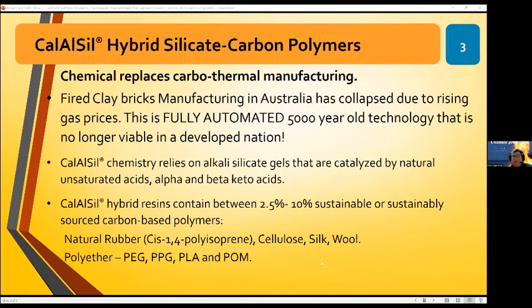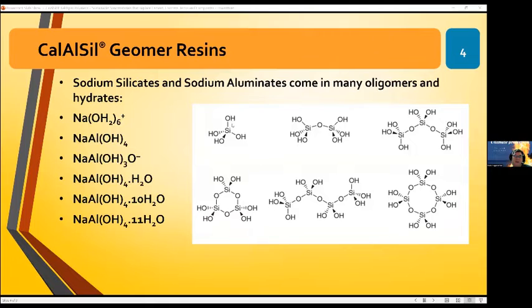And suddenly I've got a product that, because the organic component's far, far less than 50%, the maximum component I've got up to is 30% of the solid. It's about 65% solid, 35% water, sorry. So that's the 30% of the solid is organic. It simply just cannot hold a flame. So it's by design fireproof. So just trying to give a quick overview of the chemistry.